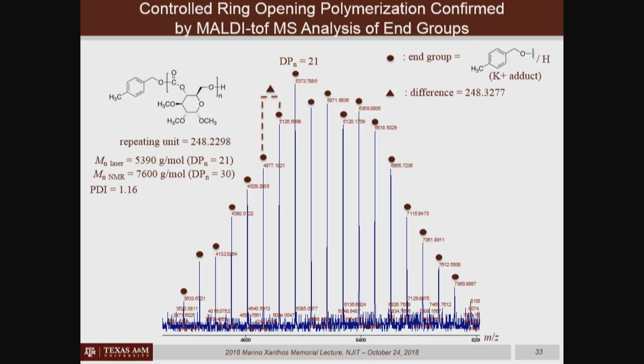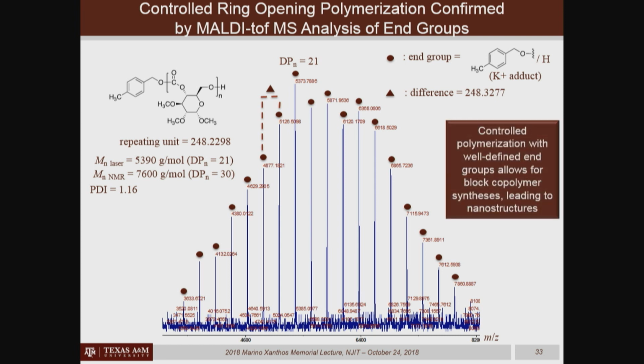And Koichiro showed that he can control the degree of polymerization. By MALDI-TOF mass spectrometry, he also confirmed that each of the polymers, and we have different polymers of different degrees of polymerization here, where we have one with a degree of polymerization of 21, 22, 23, 24, 25. So we still get a distribution of molecular masses and degrees of polymerization, but each one of those species has the initiating end at the alpha chain terminus and the terminating moiety at the omega chain end. And what that means is that the initiator initiated the polymerization, the chain propagated, and then we were able to terminate it. And by that process, that allows us to get into growing block polymers, because we can initiate, grow a segment, then once that monomer is consumed, add another monomer, and then initiate and propagate that monomer so we can build these block polymer structures.